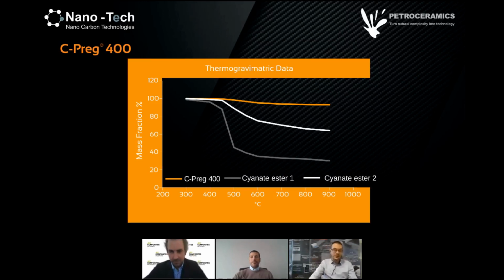Okay, so basically the special inorganic composition of the composites and of the resin allows the amazing stability of the cured composite in oxidative conditions even at really high temperatures, as you can see in this graph. We have thermogravimetric data, and here the weight loss is reported, and it is very negligible in the case of Cpreg 400, even at high temperatures such as 900 Celsius degrees. But see what happens to other resin systems that are commercially available for high temperature applications. You see the drops of the mass percentage in the curves here, which indicate that the matrix is being deteriorated at temperatures lower than 500 Celsius degrees.